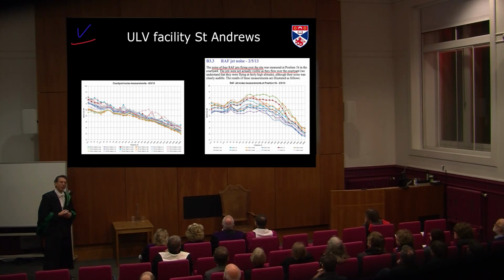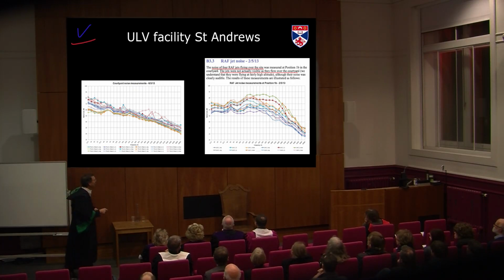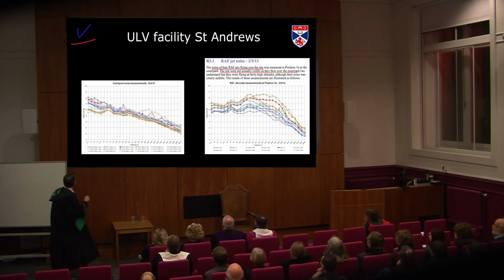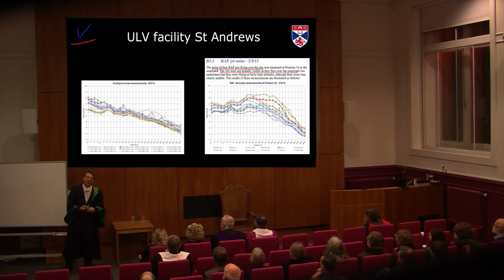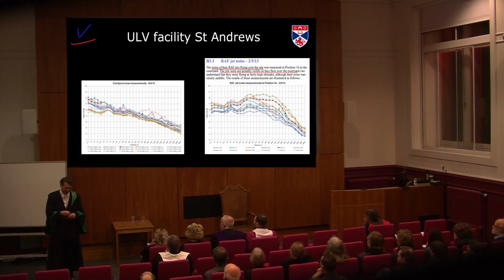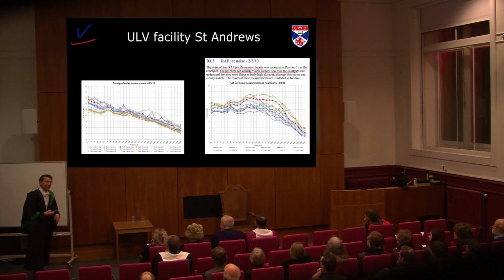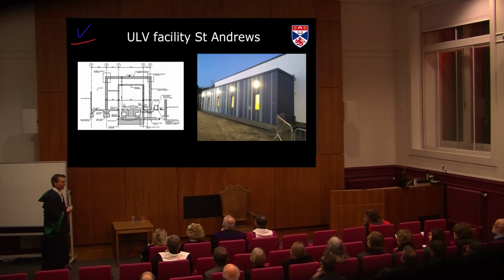But they were actually quite happy with what they saw. So this is the noise with the jets, and you see how in this part here, between 100 and say 600 hertz, it's actually quite strongly increased, right? It goes above 80, so up to here on the left graph. But what they were particularly concerned about is down here, this part. And there's actually hardly any increase. And so they were quite happy that they could deal with that and that these ultra-low vibration laboratories will be just fine, even if a jet is flying over it.